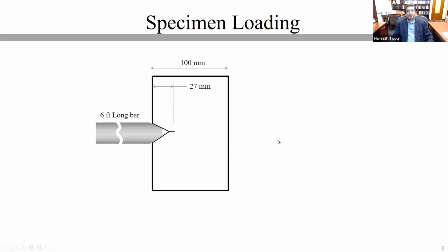despite all the problems that you face with polymer substrates. The specimen was loaded in our experiments using a 6 feet long bar. It's a long bar so that we can get a one-dimensional wave to travel and impact the specimen. We launch a striker, and it creates a stress wave that loads the specimen.